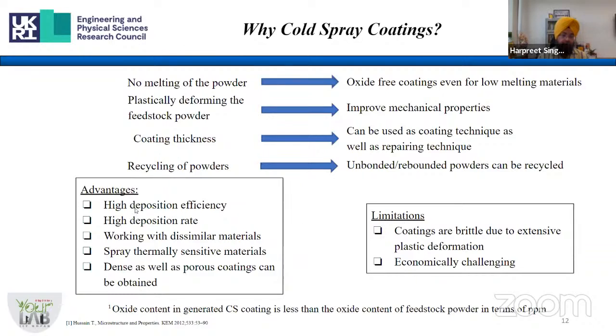So what are the advantages? High deposition efficiency, about which industry people are always worried. High deposition rates, again, we can deposit coatings with high deposition rates. Working with dissimilar metals is not that big a challenge here. Thermally sensitive materials can be processed, and dense as well as porous coatings can be obtained. So we can always tailor the coating properties, because in certain applications we need some porous coatings, as Professor Burnt was also showing in some of the turbine applications, or in biomedical applications, we usually need some kind of porous coatings.